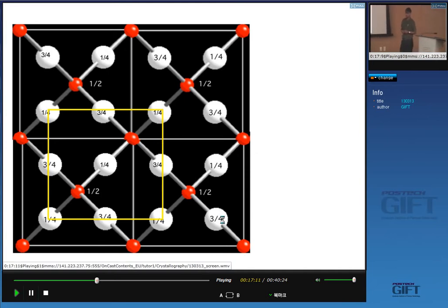I want to show you that you also have a center of symmetry in this crystal. You need to stare at the diagram for a bit. But if you focus on this region here, can you see that there is a center of symmetry here? Because look, this is at a half height. If I go through a quarter, I end up with something at zero. And you can do that for all of the atoms, and you will come up with the same result. So here, if I go from a quarter to a height half, this is the center of symmetry. If I go from a quarter to this point, I end up with another at a quarter. So there is a center of symmetry. So I can say that my threefold axis is actually a bar three axis.